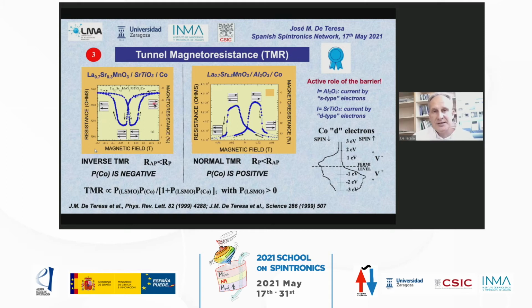And then we observed a striking result: when you use this strontium titanate barrier, the tunneling magnetoresistance was inverse. So the resistance was lower in the antiparallel configuration compared to the parallel configuration. But if we use another barrier, alumina, we observe the normal effect in which the resistance is higher for the antiparallel configuration. So how could we explain that? Manganite only had one type of electrons at the Fermi level with positive spin polarization. So the only explanation is that cobalt was changing the spin polarization.